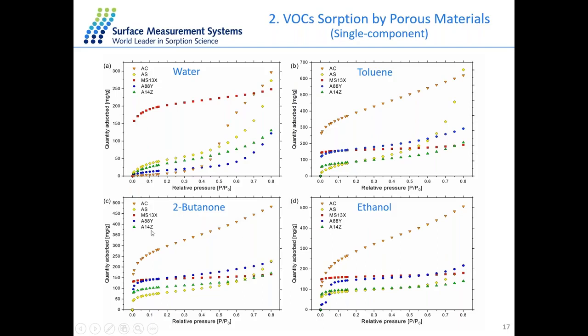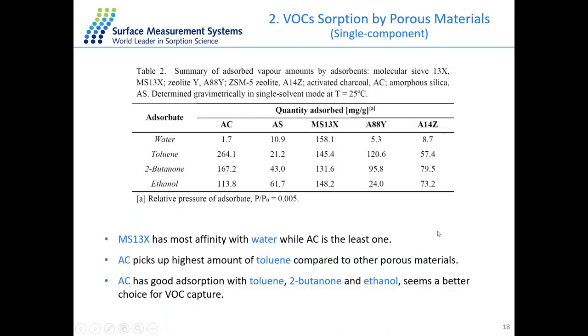The same goes for the other nonpolar molecules, compared to water, with similar behavior: the charcoal sample has the highest affinity, while the others have very similar or lower uptake, almost half of the capacity compared to charcoal. Here is a summary table with the uptake of all the different solvents at one single vapor concentration, comparing between different samples and different solvents. It's rather clear that the AC sample, the charcoal sample, has very weak interaction with water, but it has a much better affinity and can absorb plenty of the other organic vapors. So from the current set of data, we may conclude that activated charcoal seems like a better choice for VOC sorption. That's the result we get from the single component experiment.